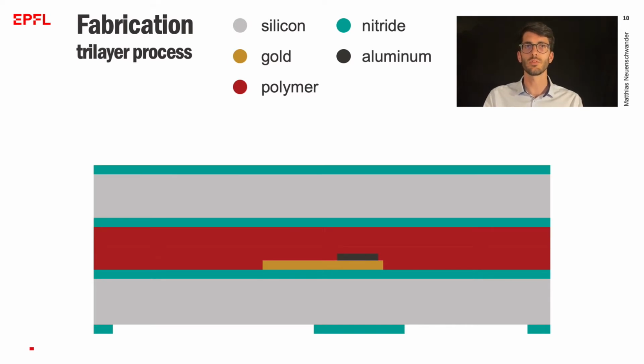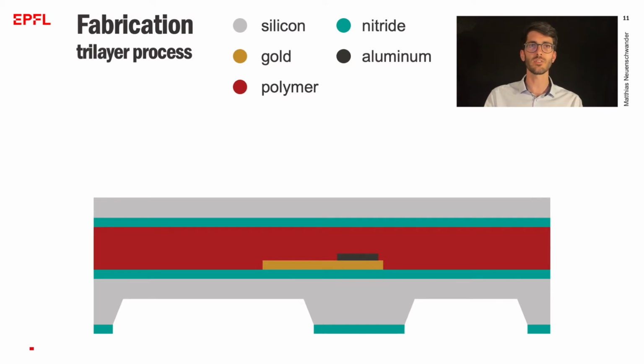We also spin coat this polymer on a second wafer. Then we bond the 2 wafers together. Note that this forms a tri-layer structure in the middle, composed of the polymer sandwiched between 2 silicon nitride thin films. Next, we etch the silicon of both wafers in KOH, and we do this until a thin silicon layer of about 15 microns remains. This we will use to create the tips.